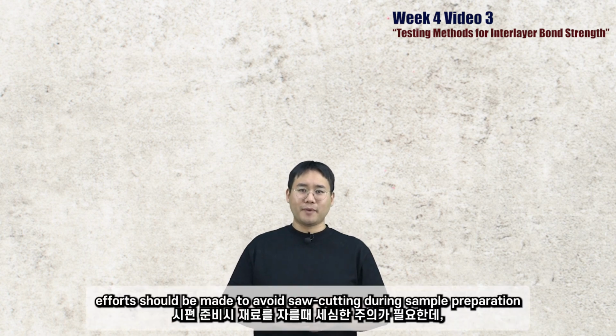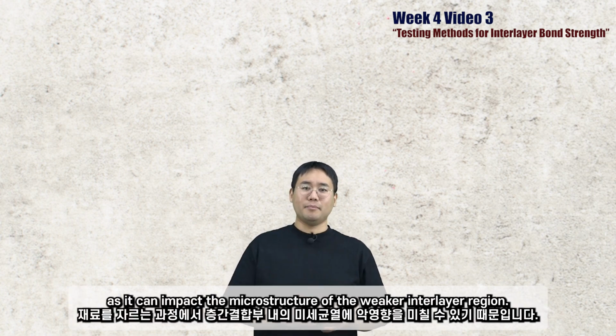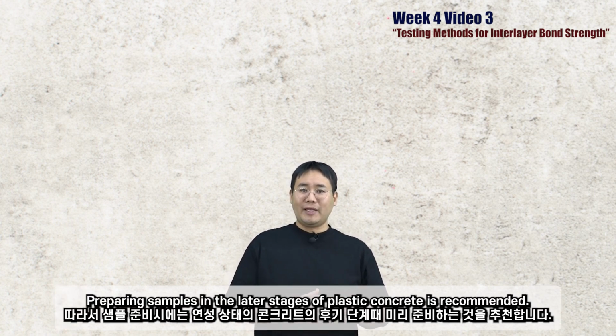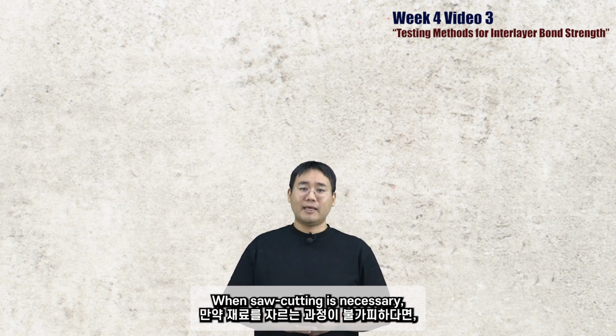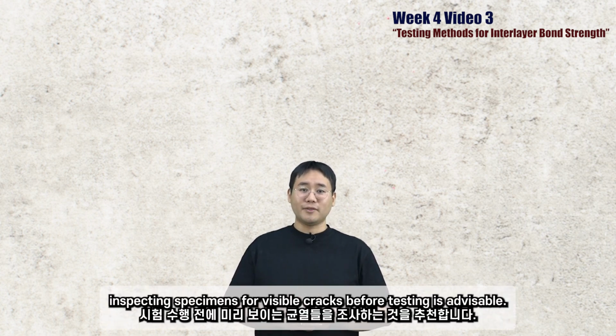However, efforts should be made to avoid saw cutting during sample preparation, as it can impact the microstructure of the weaker interlayer region. So preparing samples in the later stages of plastic concrete is recommended. When saw cutting is necessary, inspecting specimens for visible cracks before testing is advisable.